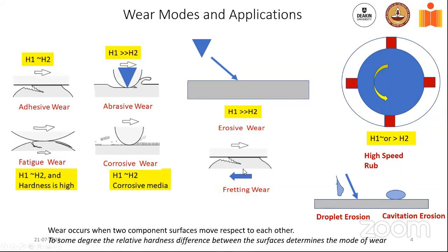The third bullet is reduce contact forces. So the one old trick as far as wear is concerned, and there would always be exceptions, but very generally, the wear increases linearly with contact stress. Higher the contact stress, greater the wear. So can you do something about reducing contact stress? And how do you do that when the aero forces are still the same? Again, there we start looking into additive because you can start building in compliance structures that would essentially reduce the spring constant of the assembly. And so for the same displacement, you don't have the same kind of forces acting on the component surfaces, and it can actually remove or reduce wear substantially.